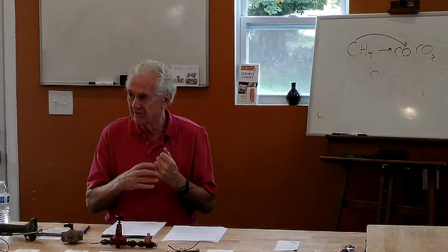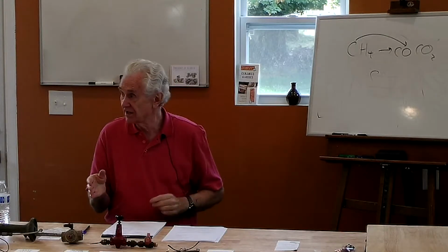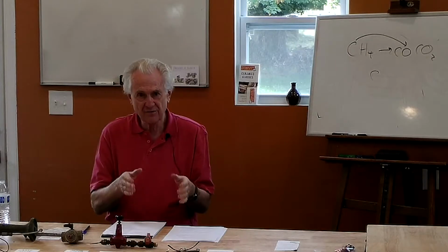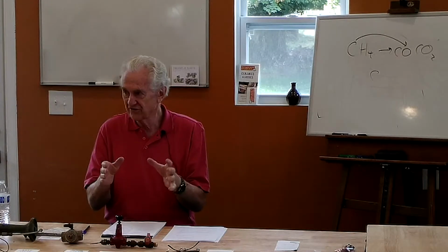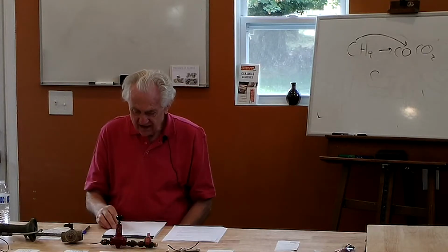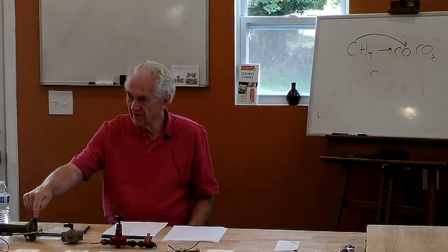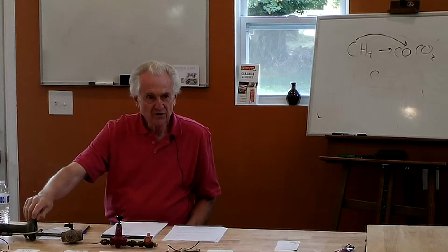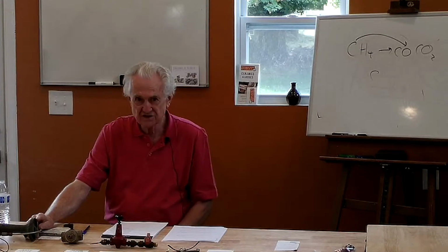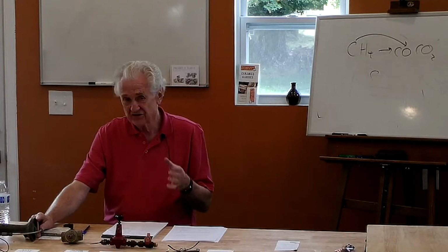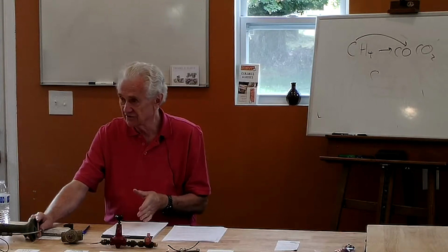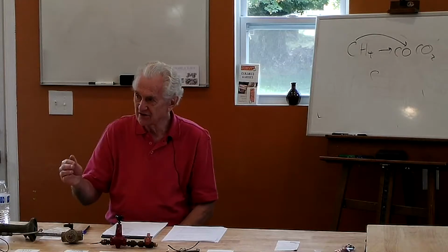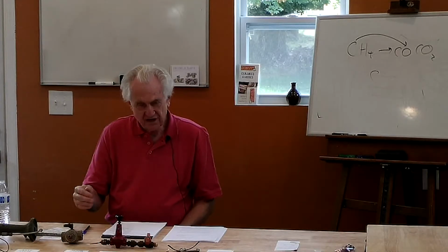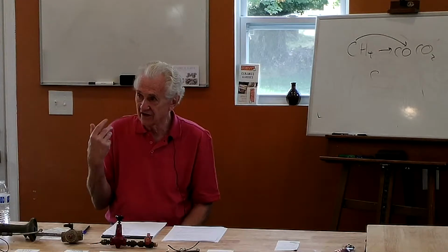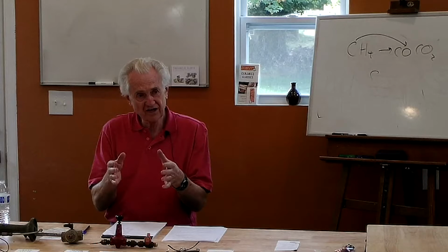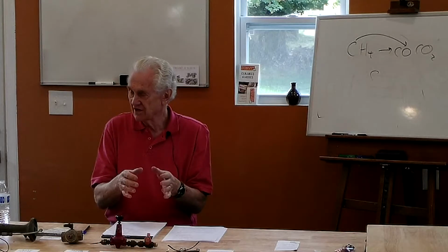You get poor carbon trapping. This is especially this category of glazes called Shino glazes, and there's a subcategory called carbon trapping Shinos, where you want to get this black deposit of soot that actually gets trapped in the glaze. And in order to do that, you need really heavy early reduction, and that's where you're going to play with the air control on the burner, where you actually change the setting of the burner and make the burner very inefficient, so inefficient that it makes soot. And it's the soot that you're actually physically trapping in the glaze to make the carbon trapping. So you need to actually make soot early on in the firing, and you need to maintain reduction again so that you don't burn out that soot, because the soot is just carbon, and before it gets a chance to get completely trapped in the glaze, if the reduction isn't heavy enough, you'll burn it right back out again.